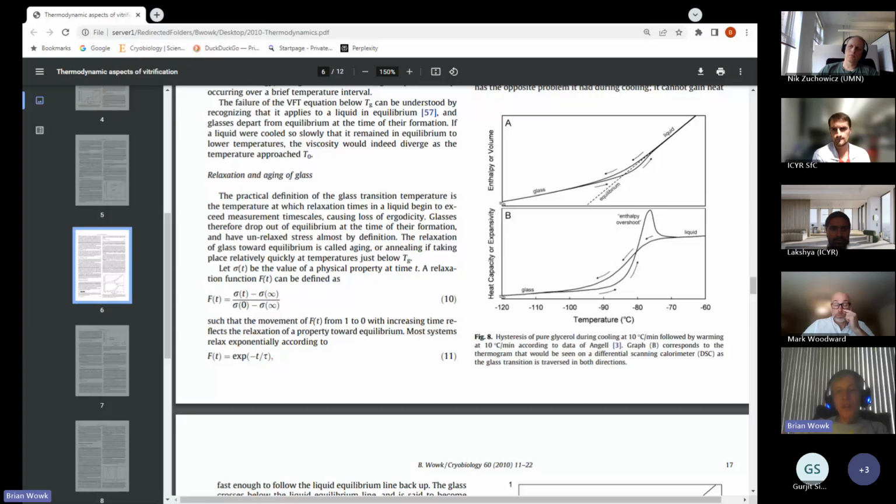And it actually turns out, this is the most interesting part I'm building up to, that with the way glass transition temperatures are usually measured in the laboratory by cooling on the order of 1 degree a minute, the glass transition, as typically defined by that laboratory measurement, corresponds to a relaxation time of about 100 seconds for all those different parameters: dielectric relaxation, heat capacity, physical density.